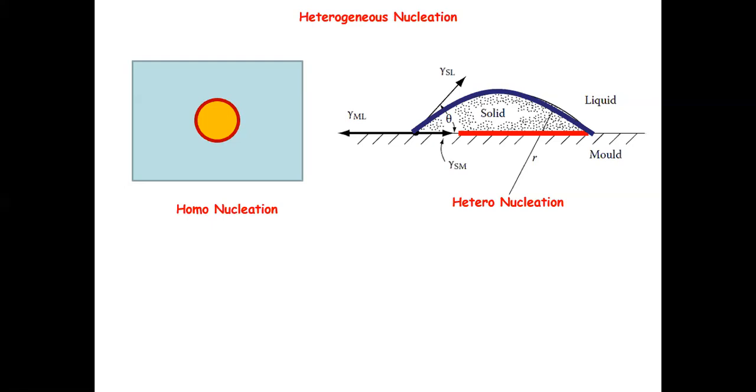Okay, so I have to move on a little bit quickly. Before we move on to talk about the free energy difference, I just want to write down the equilibrium condition for the surface energy or surface tension. Okay, so we have been calling this the surface energy, but if you check it, it actually has the same unit of force per unit length. So that's basically the definition of surface tension. Physically they are basically the same thing. Based on this interpretation, we can write down an equation that gives you the magnitude relation between these interfacial energy terms.